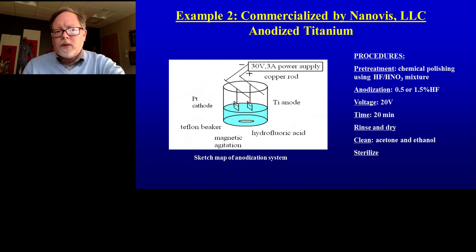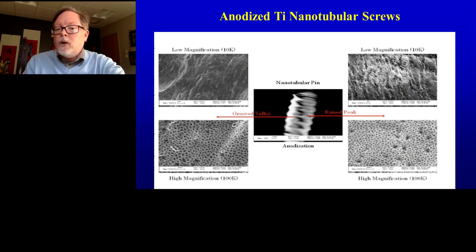Anodization is a real simple, well-understood process where you put titanium, which serves as the anode, into an electrolyte solution. We use HF, or hydrofluoric acid. You apply a voltage for a certain period of time, as indicated on this slide, and you can create nanoscale features on bone pins. So this slide shows you a low magnification image of this anodized bone pin and a high magnification picture showing nanoscale features of this bone pin.